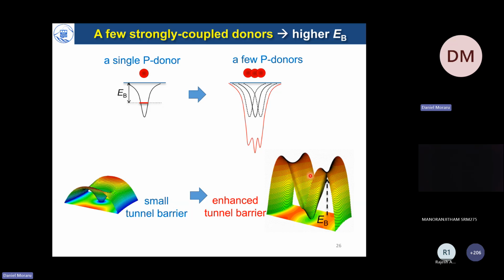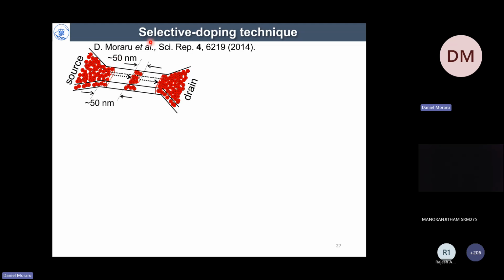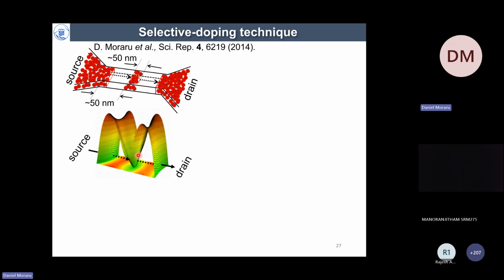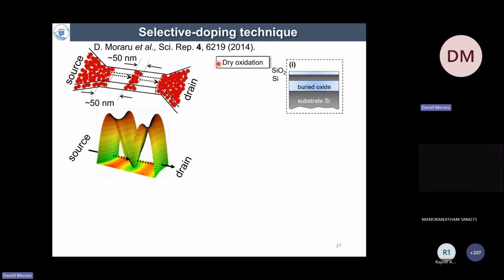To implement this kind of design, we again utilized nanotechnology and developed a pocket for doping dopants in the middle, simultaneously with source and drain, leaving an undoped barrier on each side with dimensions on the order of 50 nanometers. These were not very optimized devices, but we did hope to keep the potential well, as shown here, with a deeper potential here and a higher barrier on each side. So the simple process is also very important.